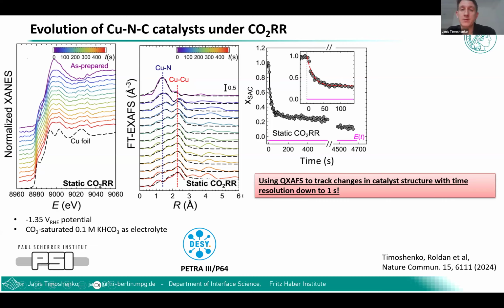And you can see that it's a process which is fast in the beginning, so this initial transformation takes 3 minutes, but then there are slower gradual changes on the scale of up to 5 hours, where the catalyst is still evolving and transforming into this more and more metallic state. So this information we can get just by looking at the X-ray absorption near-edge structure and comparing it with the spectra for reference materials.